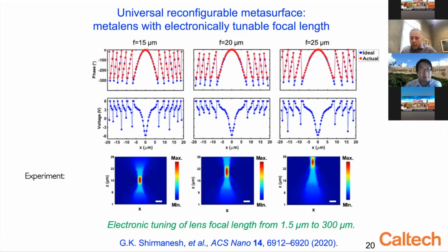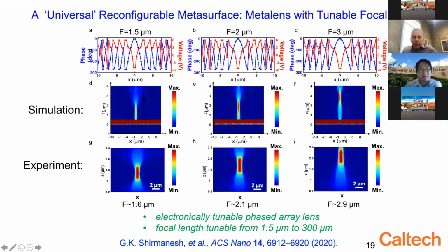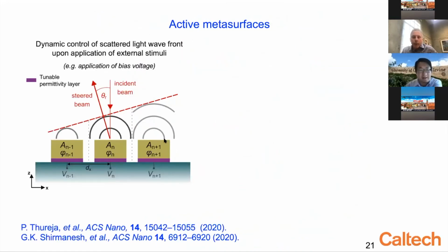So as I indicated earlier, this shows the beam spot size that you would see as a result of the full field simulation from this finite aperture. As you can see, the experimental beam waist is not quite as good as the simulated, which is probably due to random phase errors in the metasurface itself. But that gives you an idea about some of the aspects of the design of the aperture. Thank you.